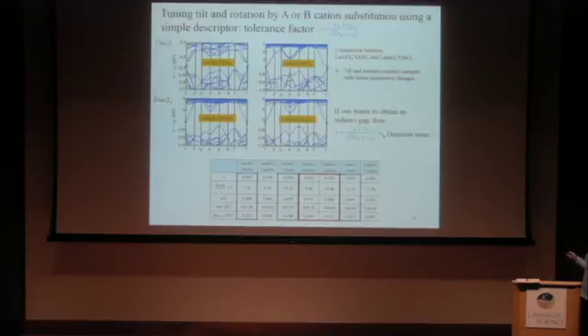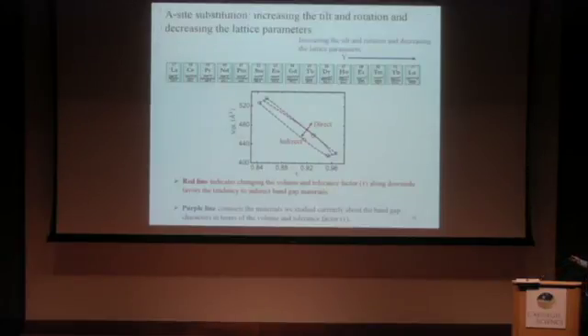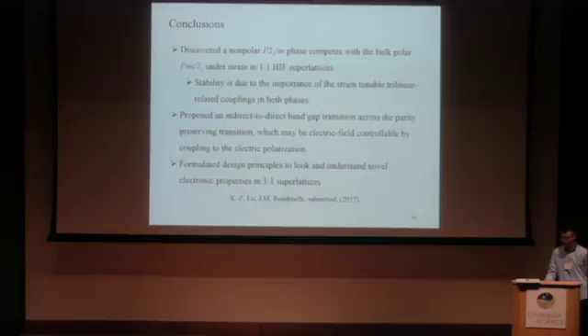And here the conclusion is that the tilt and rotation compete with the lattice parameter change. We studied many materials in the polar phase with substitution of different A-site or B-site cations to obtain this conclusion. Finally, we found that increasing the tilt and rotation and also decreasing the lattice parameter will favor the indirect band gap in the polar phase. And this is the design rule we obtained by collecting the results from the materials we studied here. And this is the conclusion.